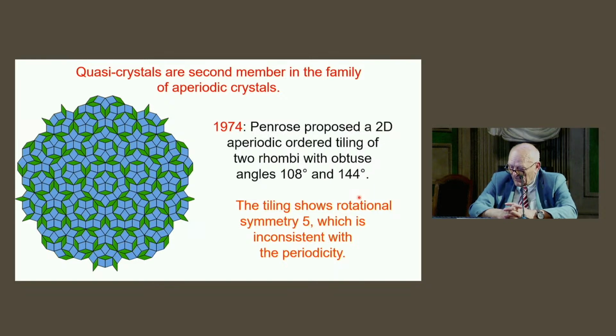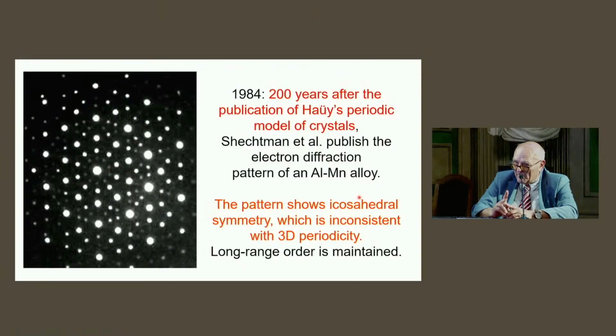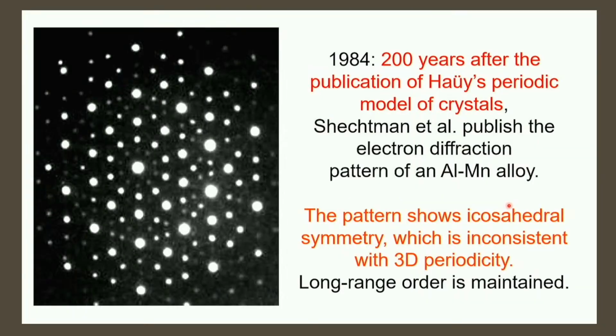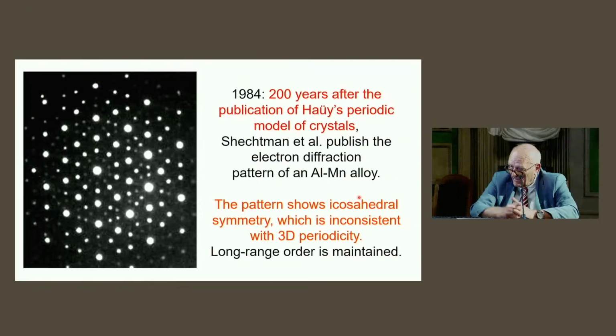And I don't know how long we're able to discuss this, because exactly 10 years ago, the experimental evidence that we can get diffraction from non-periodic materials was published, exactly 200 years after the publication of Haüy on periodicity. Sometimes history plays with this thing. Exactly 200 years later, Shechtman and co-workers published the electron diffraction pattern of an aluminum manganese alloy. Here there is diffraction, and the symmetry of this pattern is icosahedral, which is inconsistent with three-dimensional periodicity. This is just a projection, but okay. However, long-range order is maintained.